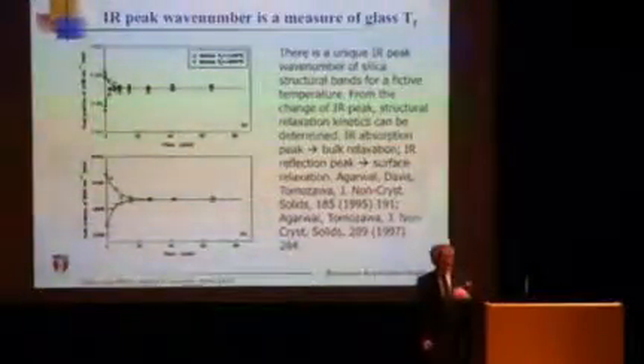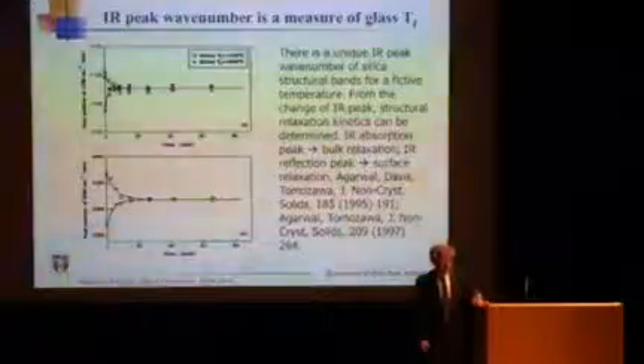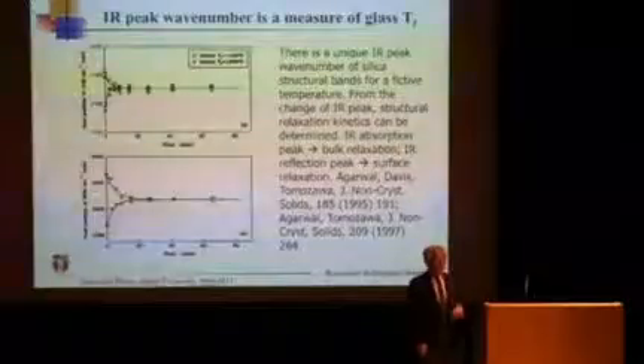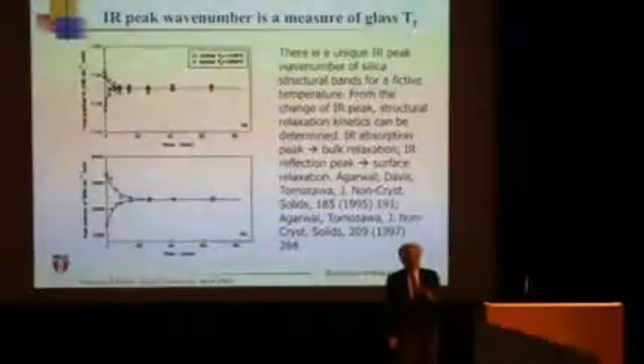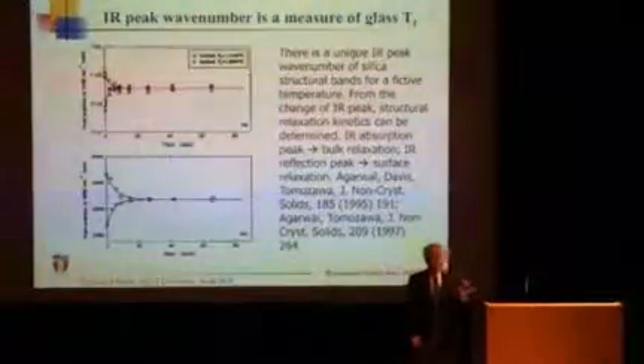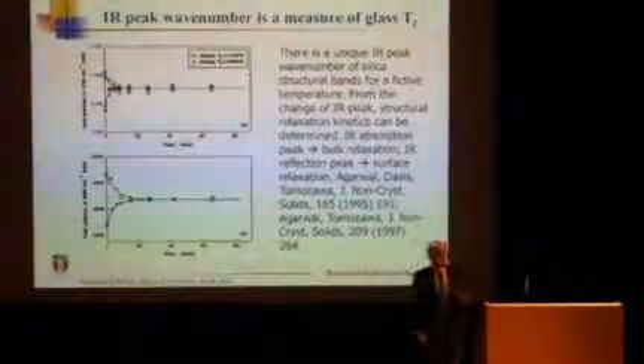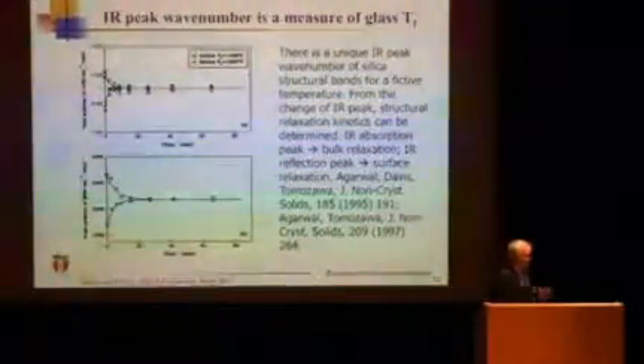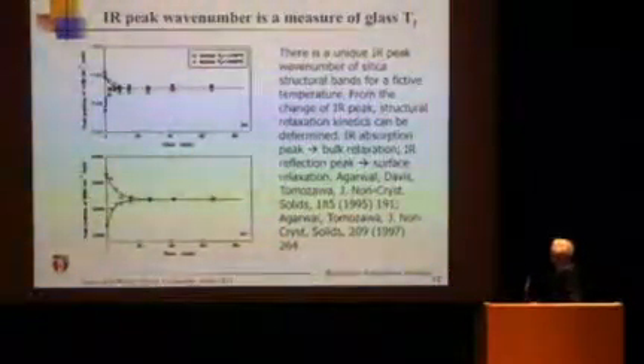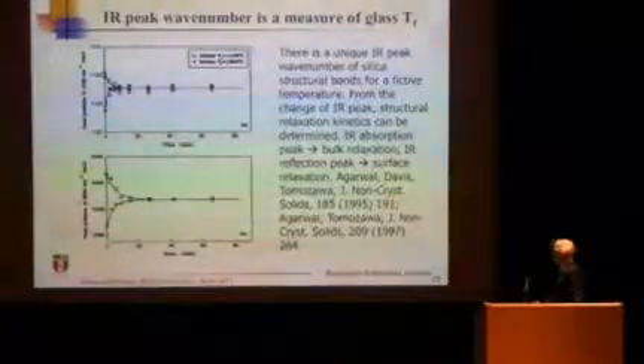As you might know, glass properties depend upon how you heat treat and how you cool. Even if you have the same silica glass, properties could vary widely. So it is important to know what the heat treatment was, what the time and temperature of heat treatment were. But nobody is going to tell you. So this way, by measuring the peak position, we can clearly tell what the fictive temperature of the glass is. The important point is that this was done by transmission, so the entire thickness was being measured.